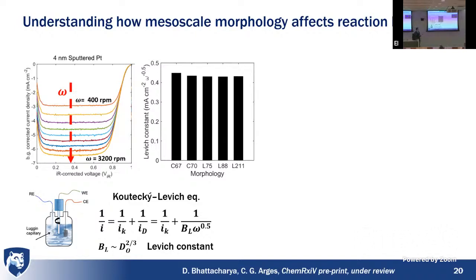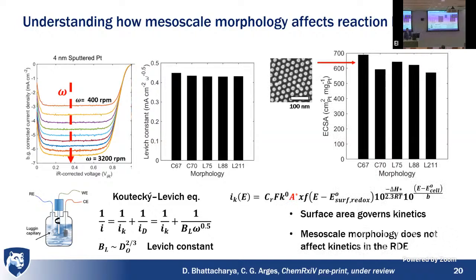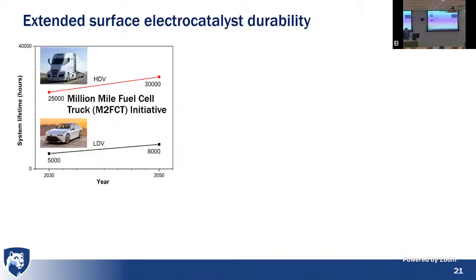I'm going to spare the long equation here, but this Levich constant is proportional to the diffusivity of the reactant to the 2/3 power. For all the different morphologies I showed you, we did not really see a difference in the Levich constant and the diffusivity. In the case of surface area, we see the electrochemically active surface area. We see that this extended surface, because it had a very, very high surface area compared to the other ones, is the reason why we got the highest mass activity. And this is important, because I did not use the most challenging block copolymer. That periodicity is a 15 nanometer lateral feature size. We can go sub 10, okay? We can do 6, 8 nanometers. So there's a lot of room to improve, but proof of concept demonstrated.